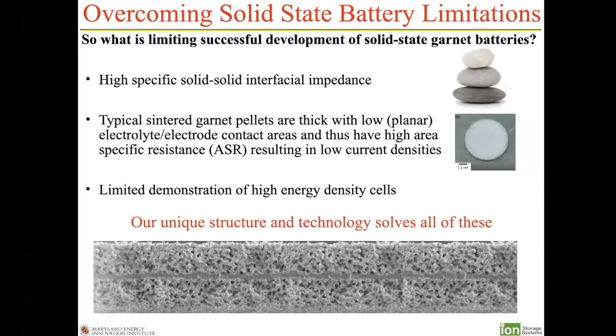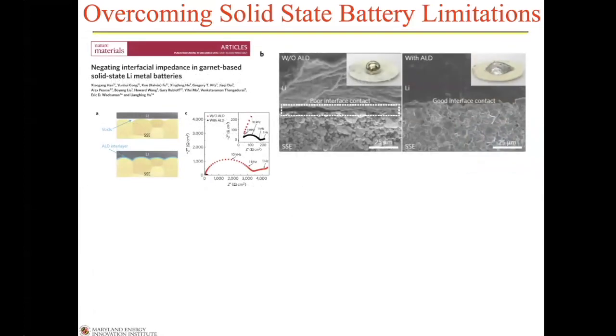So we developed a unique structure that we believe solves all of these issues. And there's a SEM photograph here. And I'm going to go through some of the advantages of why it does what it does to address these particular issues. So the first thing is getting lithium metal to wet the interface. And so if you see the photograph in the middle, what we did is we took lithium foil, we put it on a garnet disk, we heated it up above 180 degrees C where lithium melts. And rather than being a flat foil, it balls up and forms a ball of lithium metal, which will just roll off. That's classical non-wetting.